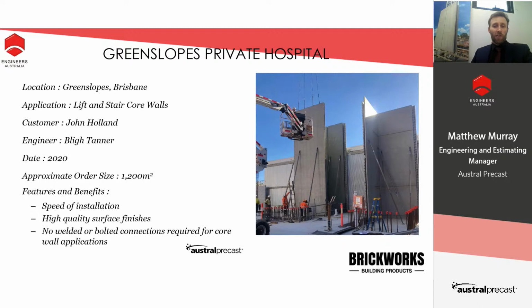So when it comes to installing these panels, we provided John Holland with a starter bar layout to ensure that all these starter bars were correct. And once that was confirmed on site, which the guys from John Holland did a very good job of, the panels were installed typically in 10 to 15 minutes per panel. If you compare this with traditional precast, where we might have, say, a dozen starter bars that might be N28s, N32s, 1.5 meter length protruding into the panel, it was a much easier construction process, and the overall result was very good for John Holland.